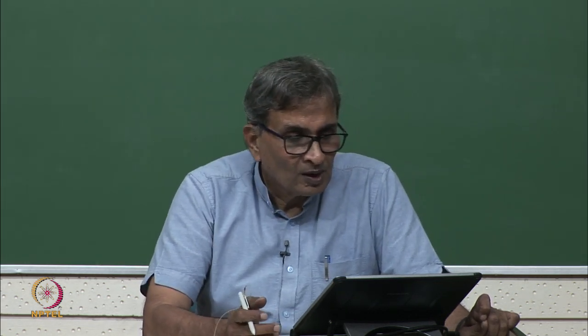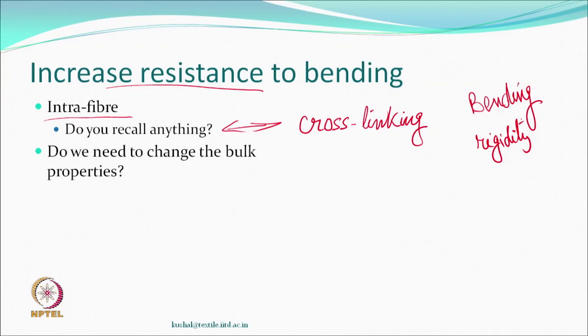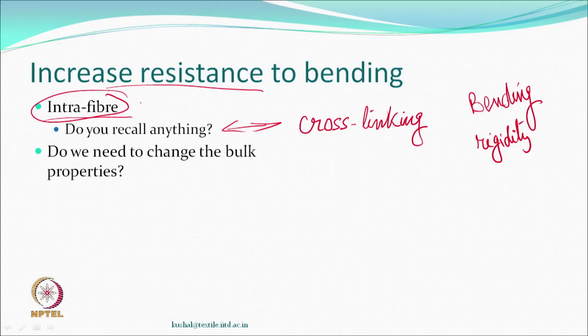However, we need not change the bulk property to achieve a stiff experience. You remember, the crease recovery, wrinkle resistant finish was a bulk treatment. That means you wanted all the molecules to diffuse into the fiber, reach various molecules wherever possible to complete a cross-linking reaction. So that was a change in bulk property. If you do this intra-fiber, you are changing the bending modulus of the fiber. If the fiber bending modulus changes, the yarn's bending modulus will change and the fabric's bending modulus will also change, and one can see the stiffness happening. But in that finish, our aim was recovery from bending.